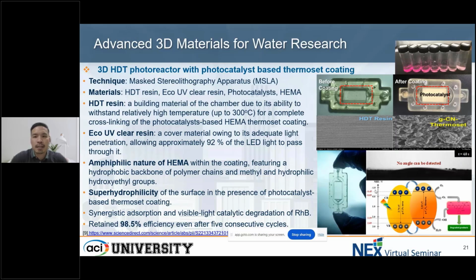We use different materials such as HDT resin and eco UV clear resin, to be coated by the photocatalyst itself. If you see the diagram, we have a before coating and after coating. We can see a clear photoreactor HDT resin with a smooth surface, while we coat with the GCN, which is a carbon nitride thermoset coating.